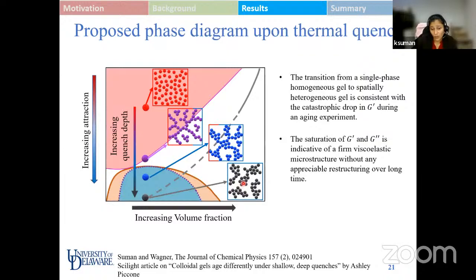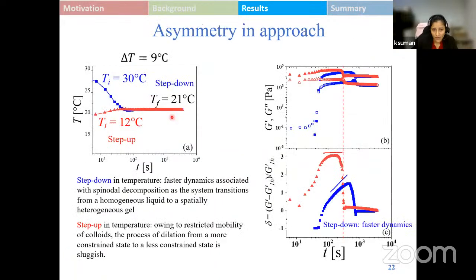So with the bulk rheological parameters G prime and G double prime, we are able to get an indication of the microstructural changes occurring in the material at different stages of aging, and how a homogeneous gel is able to transform itself, at the same concentration, into a spatially heterogeneous gel using just the quench protocol as the independent parameter. With this already known, we also try to study what the approach to the final microstructural state is if we come to that state from an identical temperature difference.